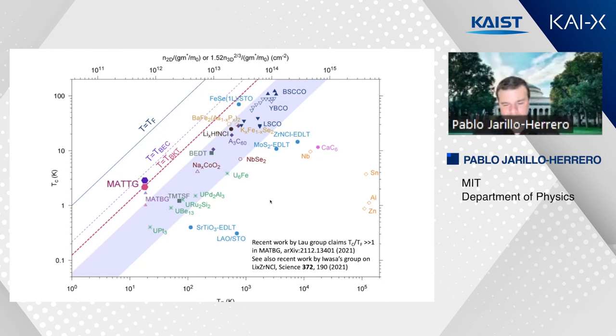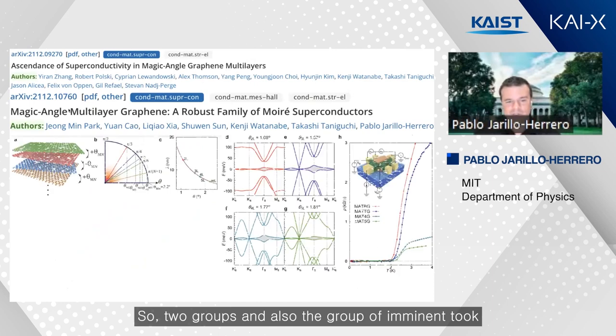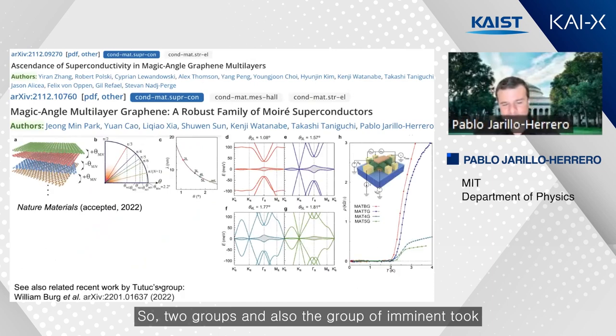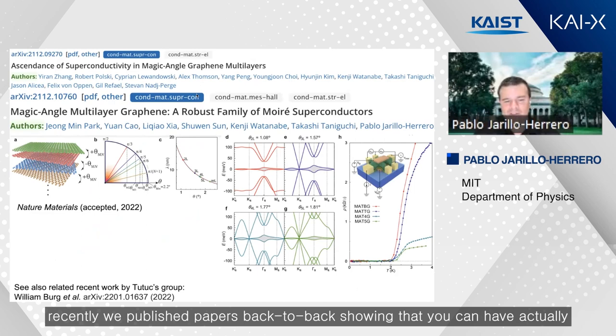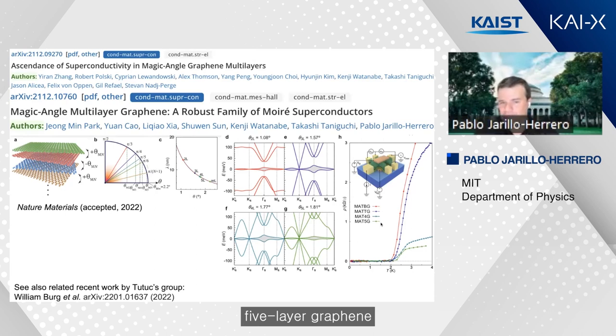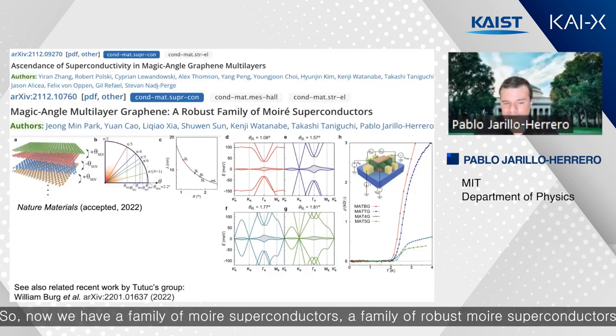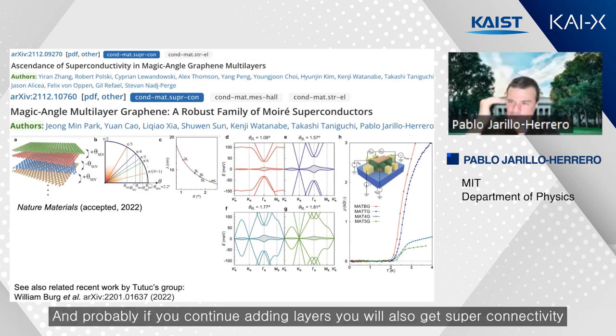So we have also measured recently not just magic-angle trilayer graphene, but magic-angle four-layer graphene and five-layer graphene, okay? So two groups, and also the group of Emanuel Tutuc, recently published papers back to back showing that you can have superconductivity also in magic angle 4-layer graphene and magic angle 5-layer graphene. Okay, so now we have a family of moiré superconductors, a family of robust moiré superconductors, okay? And probably if you continue adding layers, you will also get superconductivity.